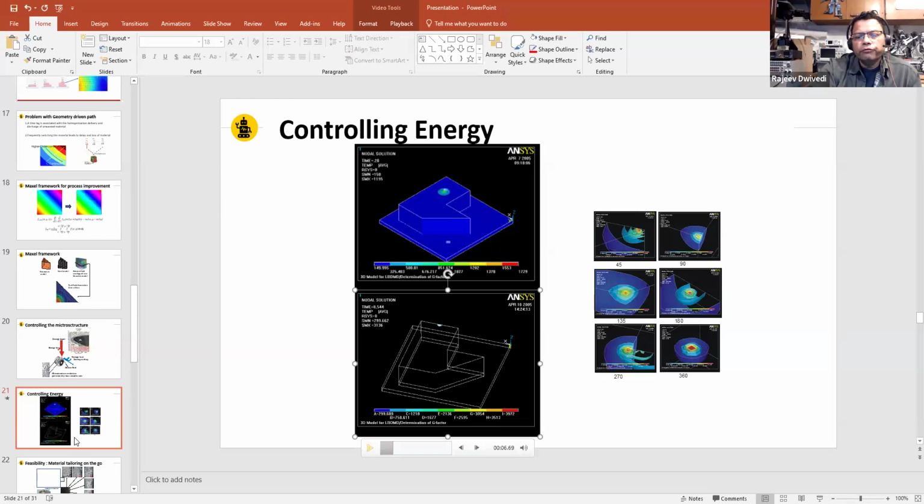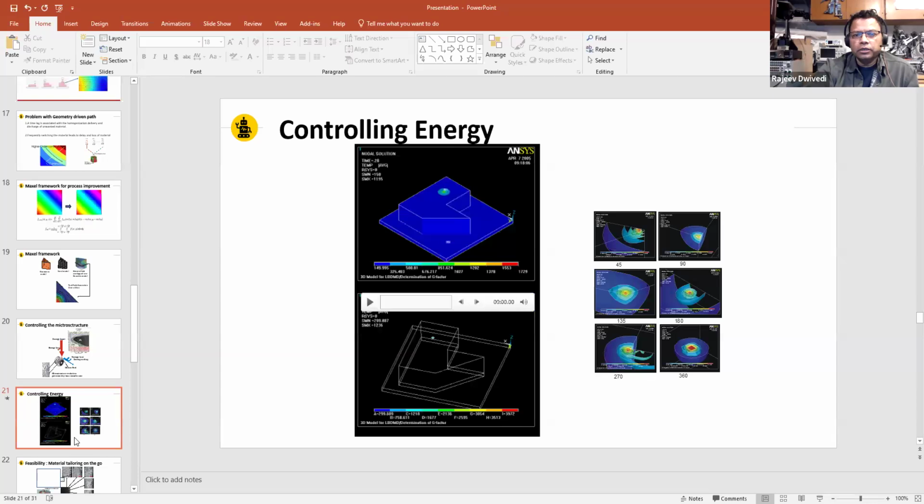Sorry. Yeah. So we decided to build, at that point of time, something called a lookup table. What the lookup table was: we had a representative bulk, and imagine my heat source, we were using a laser at that point of time, is here. I have 360-degree material around it. Here I have about 180-degree equivalent material. Here 90-degree, 45-degree, and so on. And then for the same heat, what is the impact, or the molten pool that we were generating. By modulating the extent of heat and the equivalent geometry, we were able to come up with a lookup table of what control we have to apply on the heat source so that it stays uniform and the rate of cooling stays uniform, and I'm able to get the desired microstructure.